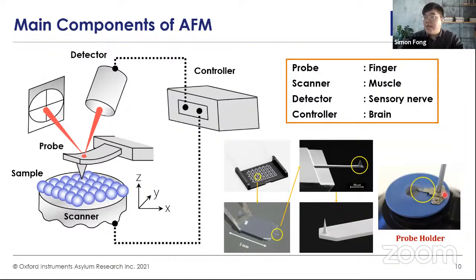This slide shows a schematic diagram of a typical AFM. As illustrated previously, we use a mechanical probe, which we call a cantilever. If you can see at the bottom right here, it shows how small the probe or cantilever is. It normally comes in a box of 10. The size of the body is around 3 mm, and at the end of the body, there's a lever which extends out of it. At the end of the lever is the tip, and this is where it touches the sample physically. The typical radius of this tip is around 10 nanometers.